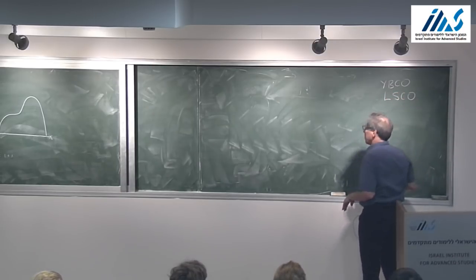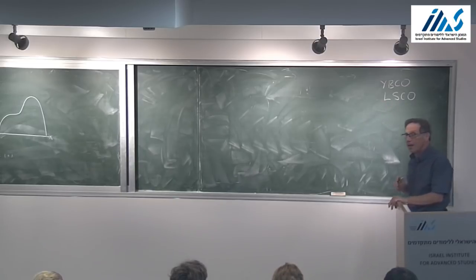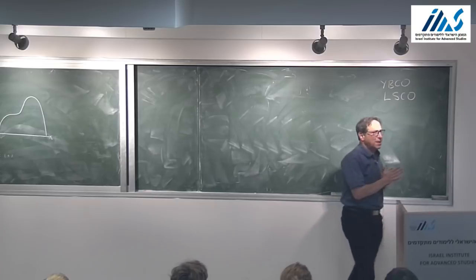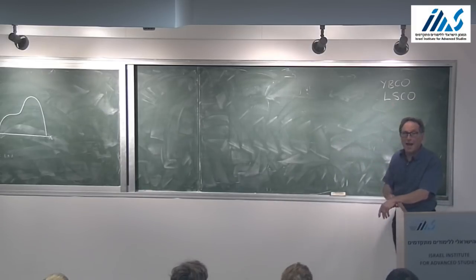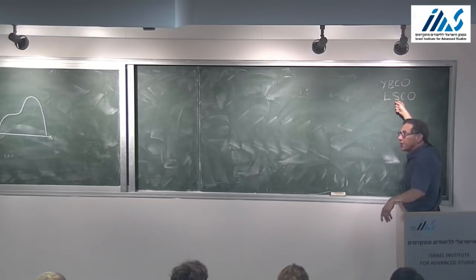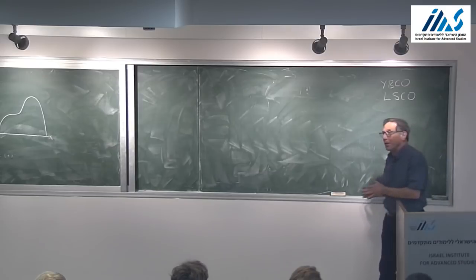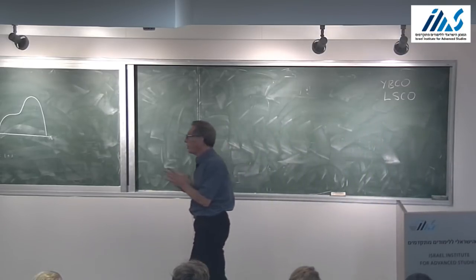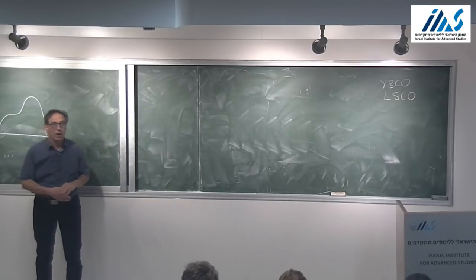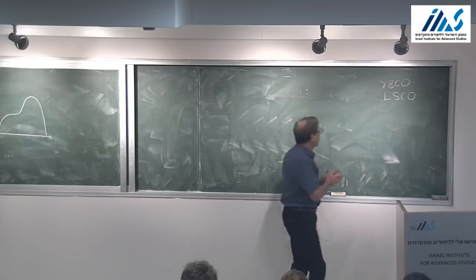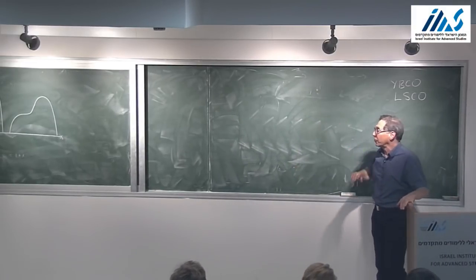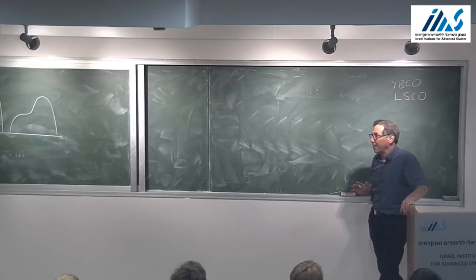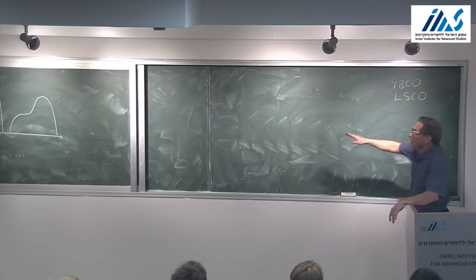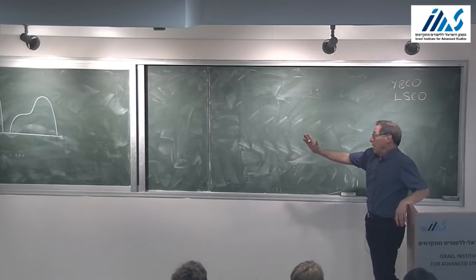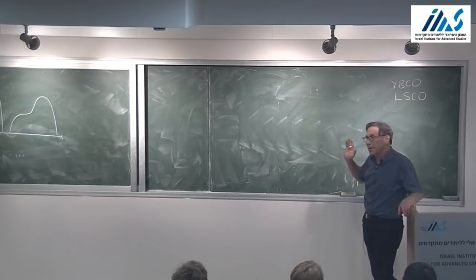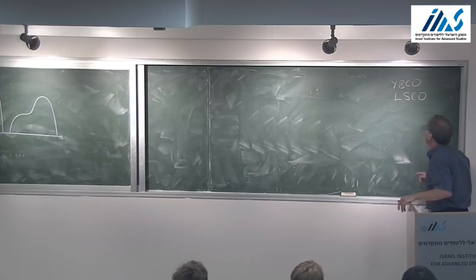Another family is the so-called 214 family, of which lanthanum, strontium, copper oxide is the most studied example. This is actually the only material where one really knows what X is. X is strontium. As you change the strontium content, all of the strontium goes in as an ion, so you know exactly what its charge is, so you know exactly what the concentration of holes is in the copper oxide plane. So in fact, every phase diagram that everybody's ever drawn is in some sense reference to a phase diagram of lanthanum, strontium, copper oxide. It's also the only material where one can really dope across this whole range of doping, and so actually have a phase diagram for the whole range of doping.